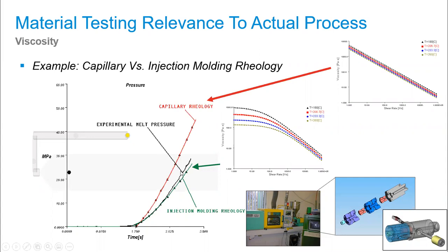So it just shows that, to answer your question, Nelson, we've seen these types of differences, and it may be below and it may be above, it depends on that fit, but because we're doing lower shear rates, we can get somewhat into the range right between 1,000 and 10,000, which is really where most rheometers operate, and we use a dual bore type of rheometer for our capillary rheometer. There are some where you can approach that 10,000 range, but we definitely can't get up into the million range.